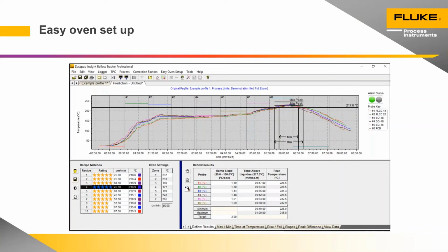The software's proposed these settings, enter them into the oven, conduct a confirmation. You've then got, in your system, the original profile that we started with. We have this prediction that the software is making, and you have your confirmation profile that you've just measured. And in the software, we do have a feature that enables you to overlay one file on top of the other. So you could have the original, the predicted, and the achieved overlaid one on top of the other to be able to analyze them and check the accuracy, if you like, or the efficiency of the recipe calculation system.